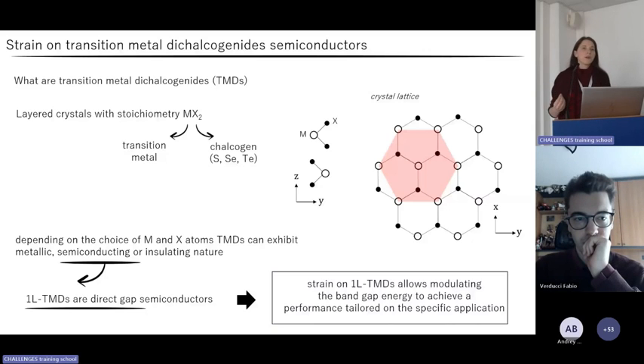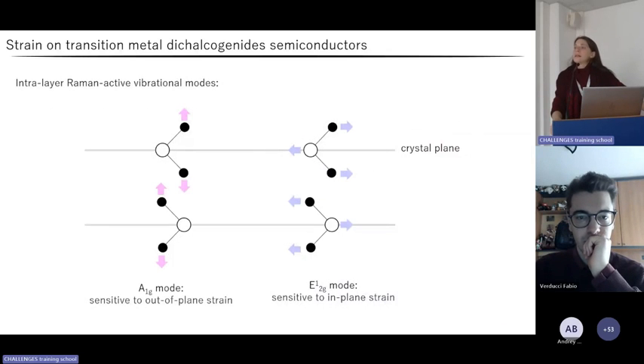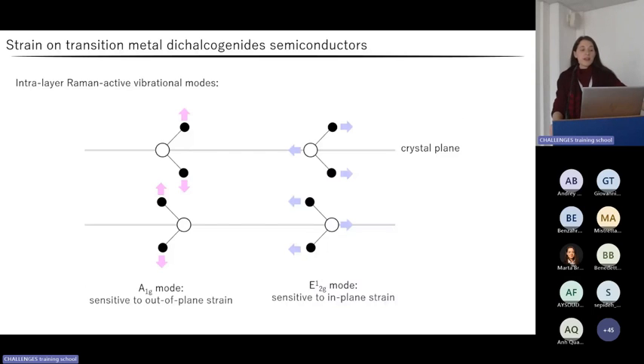In this framework, methods for strain engineering were found to be particularly effective due to the quasi-two-dimensional nature of these semiconductors. A very powerful tool to optically characterize the response of TMD semiconductors to the application of strain is looking at their vibrational modes in the Raman spectrum. In fact, in TMD semiconductors, intralayer Raman active modes involve lattice displacements with a very well defined directionality, either out of plane in the case of the A1G mode or in plane in the case of the E1-2G mode. The way the frequency of these vibrational modes changes under the application of strain is therefore strongly connected with the nature, with the direction of the deformation applied to the crystal lattice.